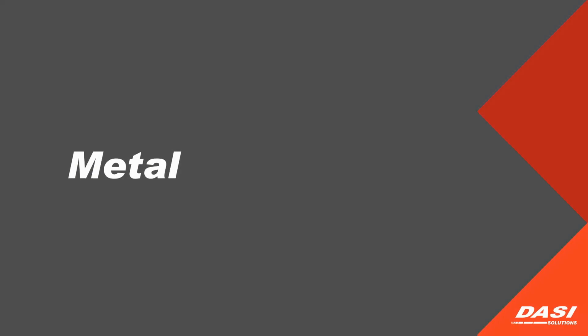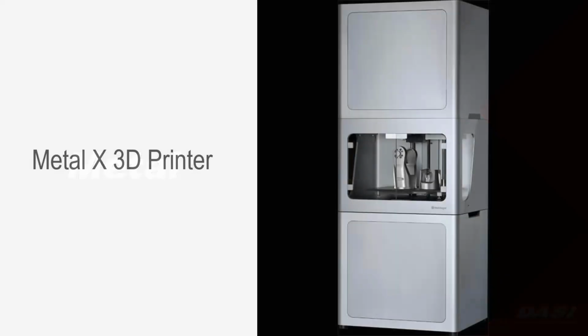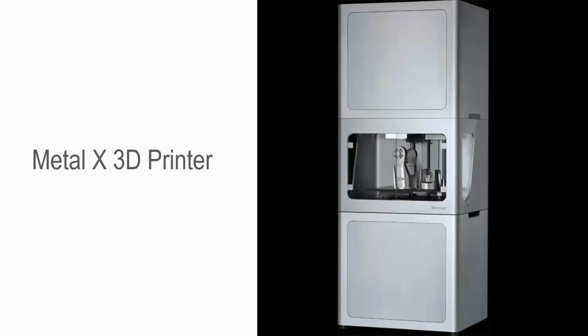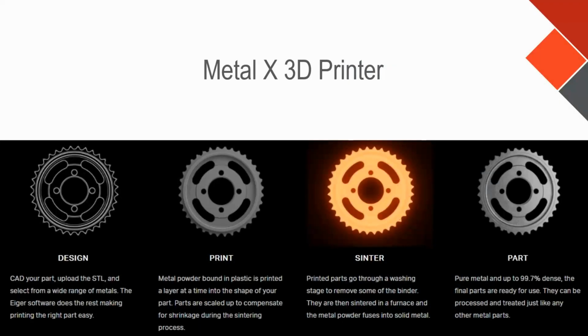Now, metal is really where the industry is going to be revolutionized, and it's going to come down to the way that these parts print, their speed, and the ability to use them even up in the highest applications like turbine motors. Essentially, you're printing them in traditional methods, but we print it with a little bit of a powder-bound plastic, and the plastic has metal built into it. So the software builds the part larger or smaller as necessary so that when the plastic is obliterated during the sintering process, it will equalize to the proper dimensions that the part was designed to.